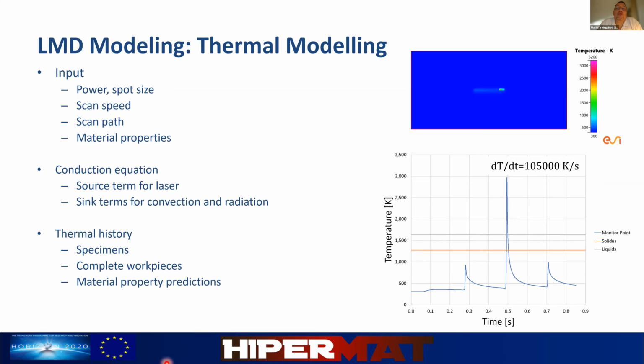One peak, the first one, is as the laser approaches the point of interest, we see a small peak. It did not achieve any melting. Then the second peak is when the laser crosses that point, we have significant melting. And then we have a quick cooling with a cooling rate, which is quite high. And then we have a third peak, which does not remelt the material. That's as the laser comes in the vicinity, but it's moving away from that point of interest.